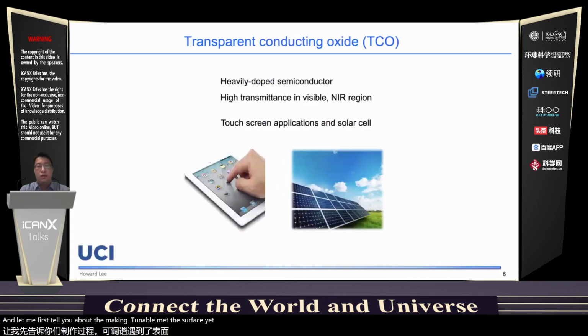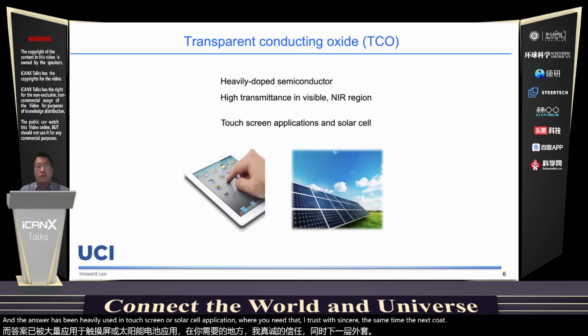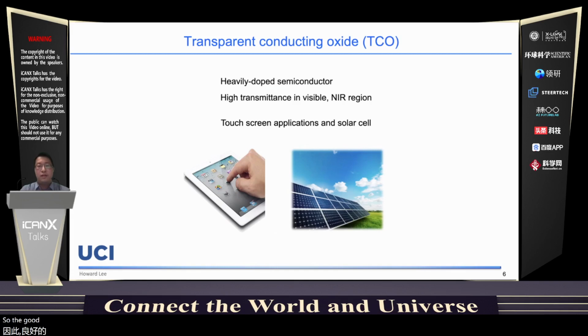So the tunable material we're using is called a transparent conducting oxide, which is a heavily doped semiconductor. They have high transmittance in the visible and near-infrared range. And they have been heavily used in touchscreen or solar cell applications where you need high transmittance and, at the same time, electrical conductivity. So the good thing for this conducting oxide material is you can actively control the optical property here.